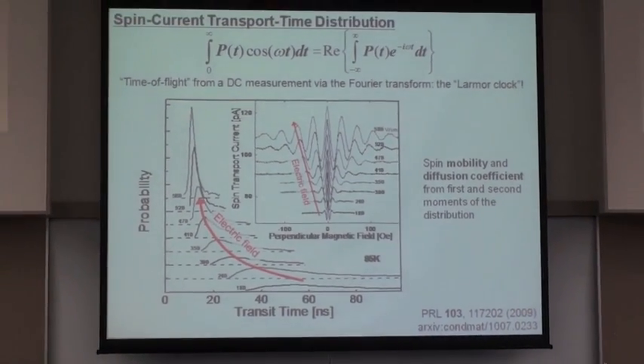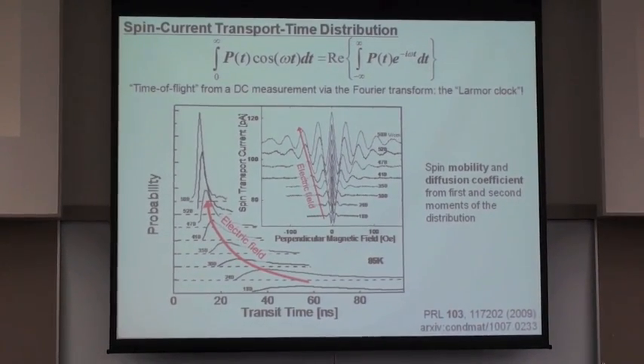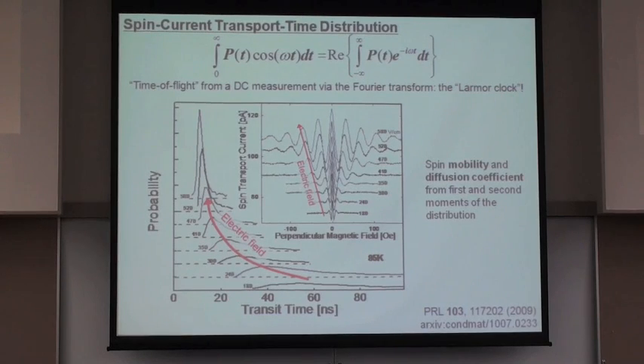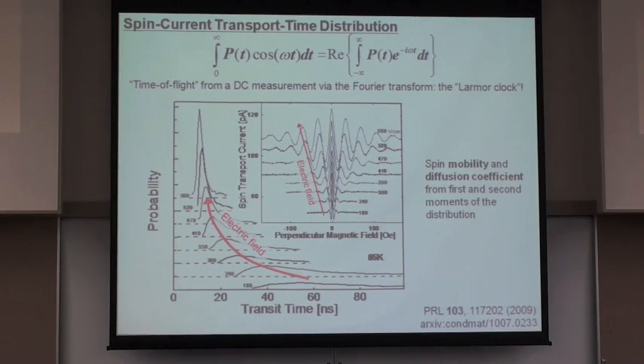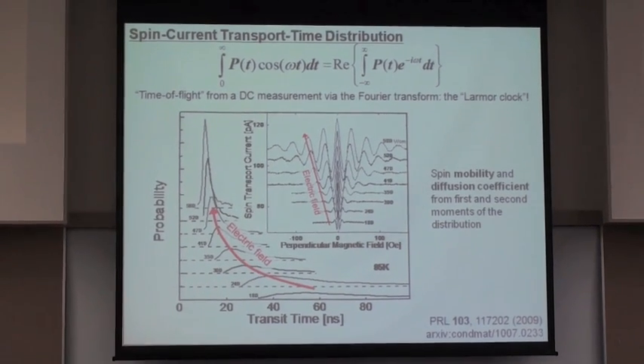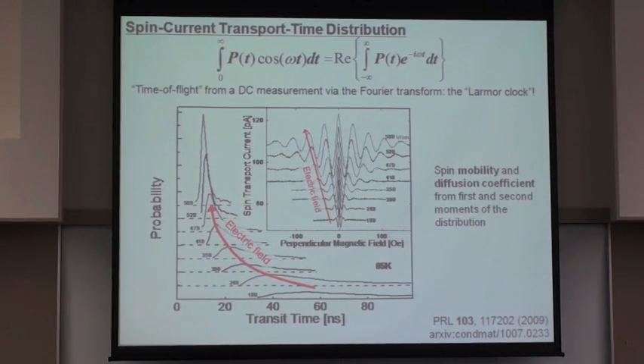Now, one of the powerful things that we can do here is, since we can, by the use of these spin precession measurements, determine the mean transit time, we can then use these measurements in conjunction with in-plane magnetic field measurements to determine the spin polarization, to then see the relevant time scale for spin depolarization.